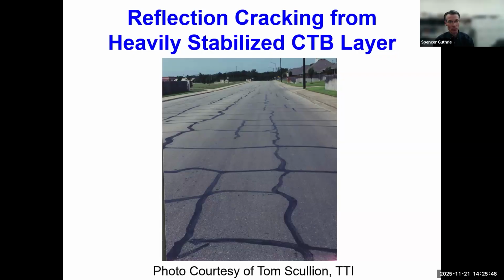I worked in the flexible pavements division at Texas Transportation Institute, and my supervisor was Tom Scullion, who provided that picture. Not pretty, structurally sound, yes, but there's some roughness here that we would like to avoid, and some maintenance issues, the crack seal, we'd like to avoid when we over-stabilize and cause the shrinkage cracking.